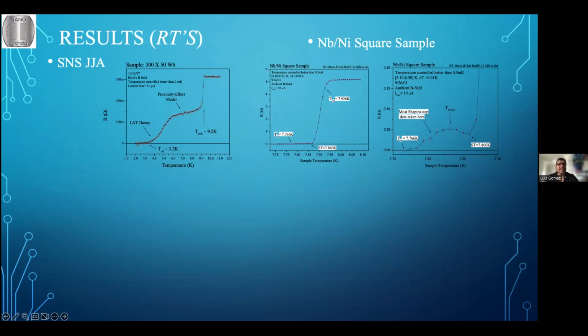Okay, and then this is the other system. This is the niobium film on top of the nickel square dots. So again, you have a region where the material is normal. The niobium film hasn't become fully superconducting, but the nickel somehow affects the niobium. So the resistance starts lowering, not as sharply as on the first sample, which is more clean. You have gold that is not magnetic.